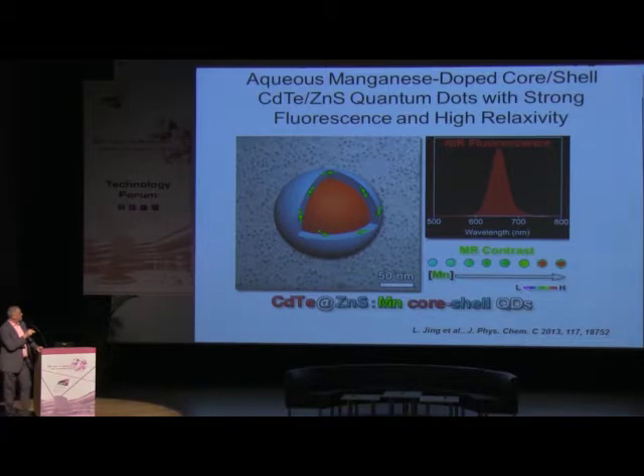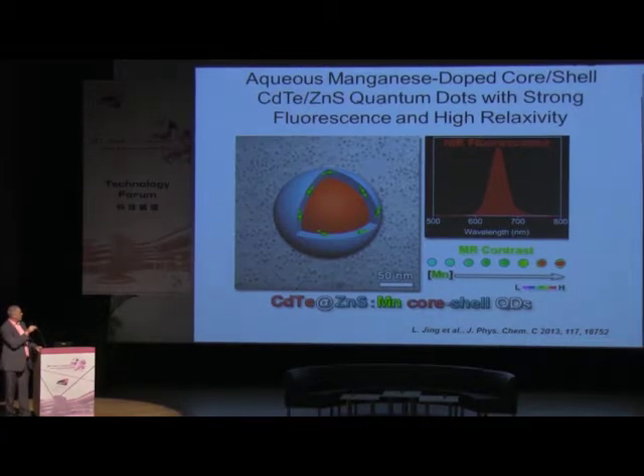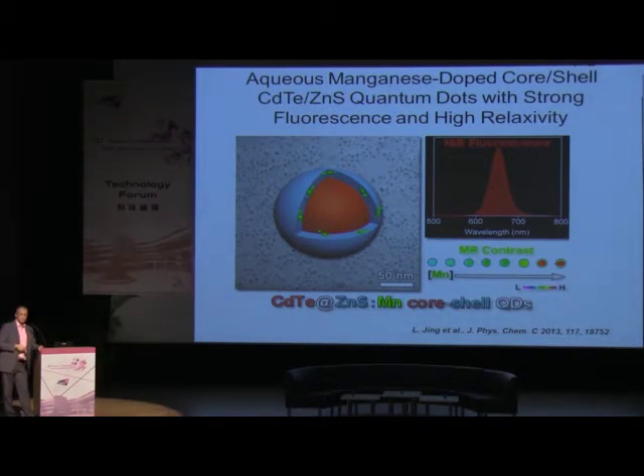And here, we created something more complex. We call these particles core-shell, because we start from a cadmium telluride core, which gives us this emission in the near infrared, 650 nanometers. We coat them with a shell of zinc sulfide. By that we reduce toxicity of those nanocrystals. And then we also put some dopant into the shell, which is manganese. And manganese is a magnetic resonance contrast agent, which means that we can follow those particles in a body, for example, both by near-infrared emission and by doing MRI measurements, which is very useful for a number of reasons.